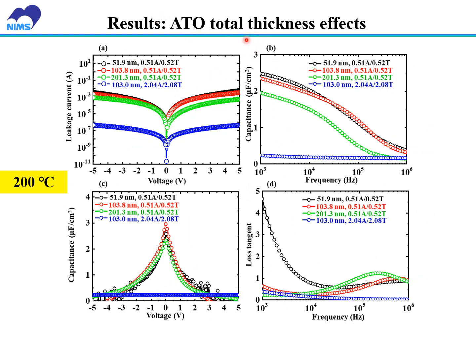Next is the total thickness effect on the electrical properties of the capacitor. The deposition temperature was fixed at 200 degrees C. The total thickness was changed from 50 nanometers to 200 nanometers, and the sublayer thickness was changed from 0.5 angstrom to 2 angstrom respectively. For the case of a sublayer thickness of 0.5 nanometer, increasing the total thickness does not affect the leakage current and the capacitance maximum.